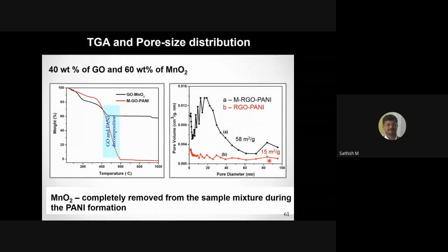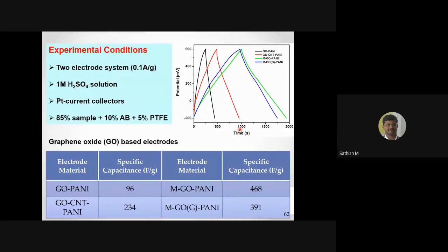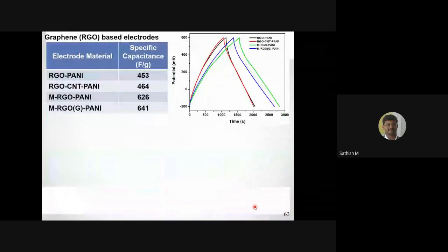We have also measured the surface area. This case is 15 meters squared per gram, whereas with the manganese oxide route, the graphene polyaniline composite is 58 meters squared per gram. We have also done some charge discharge characteristics. You could see this is the graphene polyaniline. It's 468. If we have carbon nanotubes, it's 391. Whereas if you use graphene oxide polyaniline.